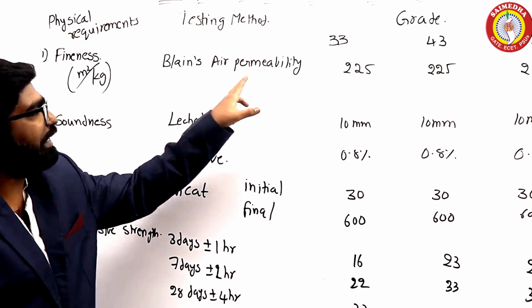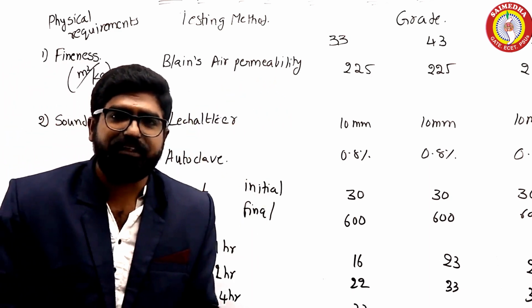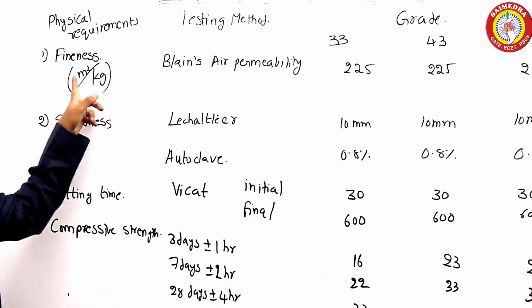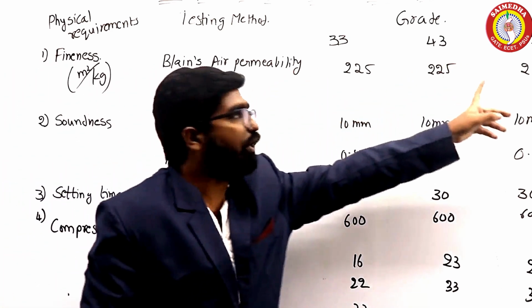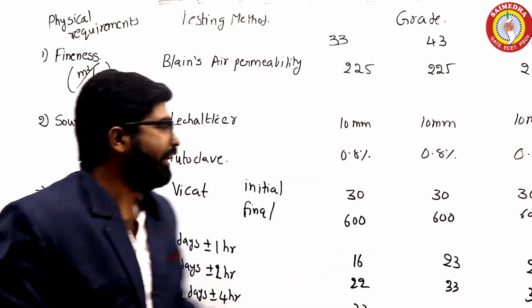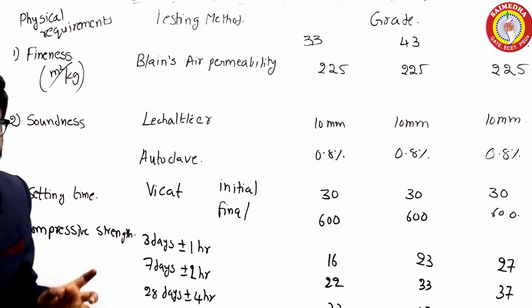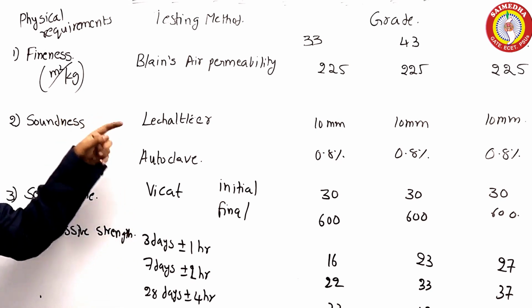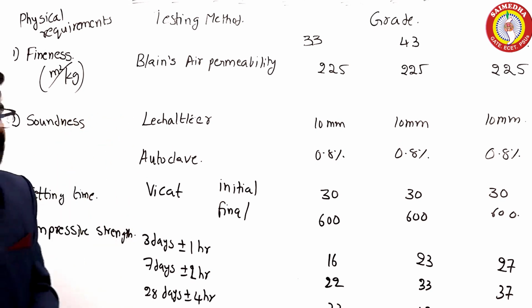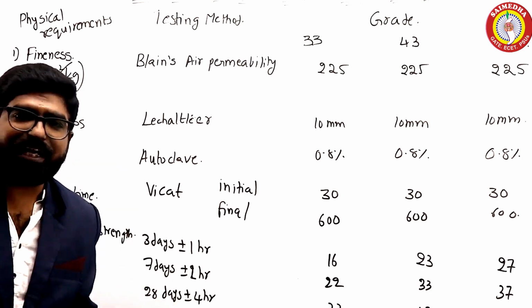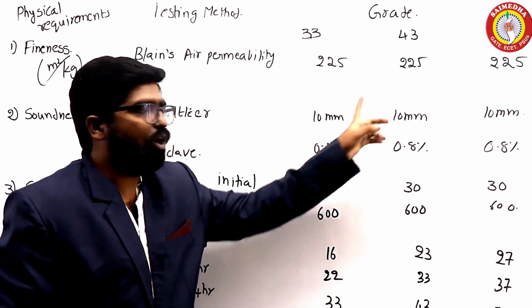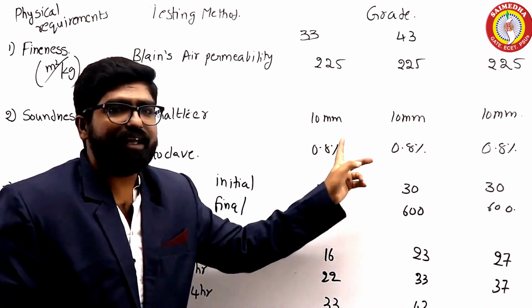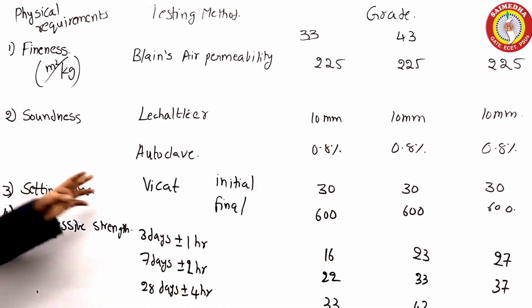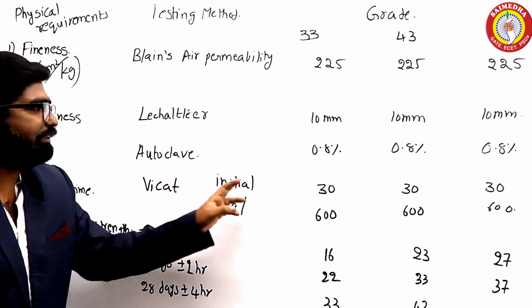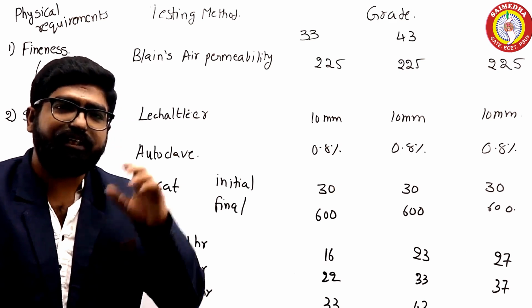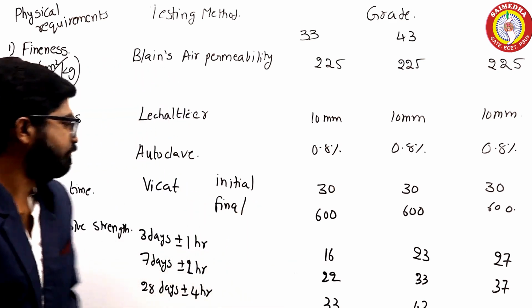When I do Blaine's air permeability test as per Indian Standards, I should get a fineness of 225 meter square per kg for 33 grade, 43 grade and 53 grade cement. Next, soundness test. I have already said about soundness. Soundness can be tested by either the Le Chatelier test or the autoclave test. If done by the Le Chatelier test as per IS standards, for 33, 43 or 53 grade cement, you should get a value of 10 millimeters. If you do the autoclave test as per Indian Standards, then you should get 0.8% soundness.